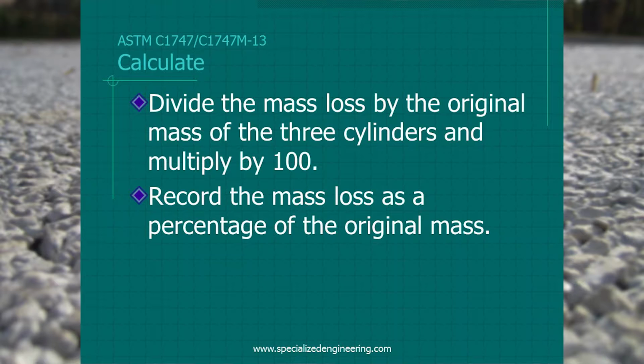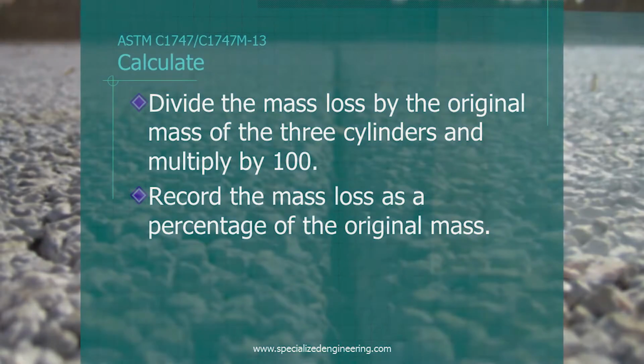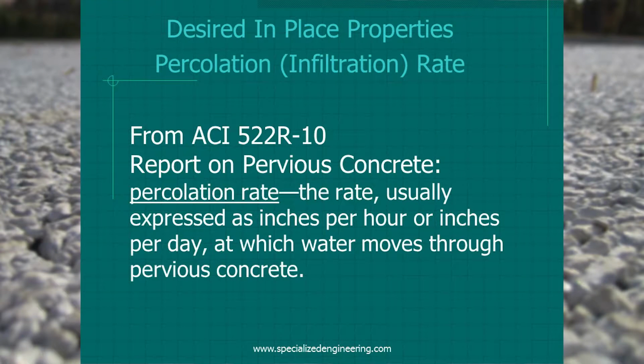I think you said these samples that are going around were about 20% loss. And that's a really good result. That's a really durable mix. But again, for the producer to make sure to compare that durability with the infiltration rate, you still got to get the infiltration rate. If we did a traditional concrete mix, it would have much less loss than that. So it's a really good tool for that. So again, that's the test for durability. So those are the two key things, durability and then infiltration.